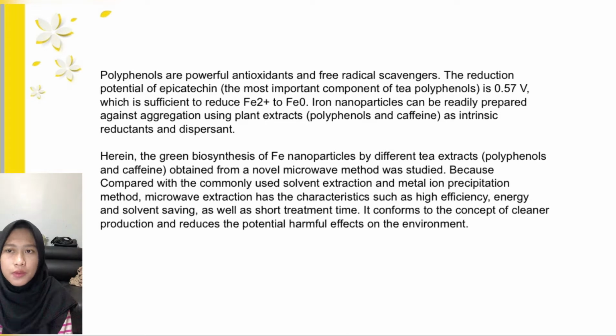The reduction potential of epicatechin, the most important component of tea polyphenol, is 0.57, which is sufficient to reduce Fe2+ to Fe0. Iron nanoparticle can be readily prepared against aggregation using plant extract, polyphenol, and caffeine as intrinsic reductant and dispersant.